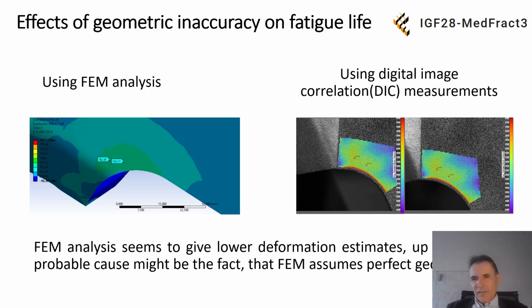When we compare the stresses from the simulation with ideal geometry to the stresses from measurement on the real geometry, here is the measurement using DIC, digital image correlation, and here are the results from the finite element method. This is the ideal geometry, and here is the real geometry. These differences are also possible to see, and it is not possible to omit them completely. This difference between real stresses and ideal simulated stresses is also necessary to add in the assessment of fatigue lifetime, and this is one of the specifics of not only bicycle frames.